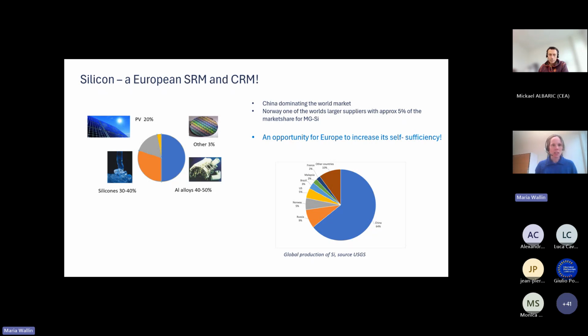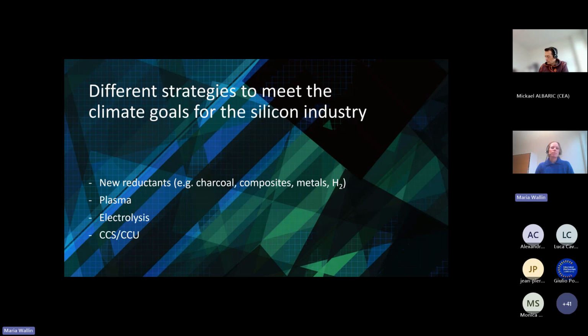And this is something I would like you to keep in mind when I continue here, because there are different strategies to meet these climate goals for the silicon industry to reduce their emissions and energy consumption. We look at different ways of doing this to support the industry. One way is to use new reductants, like replacing fossil carbon with charcoal, which is something we look at. You can blend this with a raw material, silica, make composites. So you have different raw material mixes. You can use metals as reducing agents instead, or hydrogen. It's difficult for silicon, but you can use it for other cases. Here, plasma, electrolysis, carbon capture, storage, and utilization. So there are just a few.